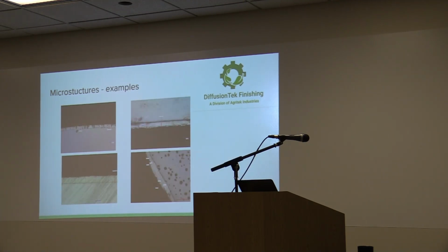Here's some other, we talked about the micro cracks a little bit, I think when we talked about sealers. And you can see in some cases these dark areas are some of the micro cracks. Now, this one probably shows it better. There's not very many. Part of our coating development was, I don't really like those. I want to get rid of those. What can we do to the formula to mitigate those kinds of things? That happens to be ductile iron. So those are graphite nodules, those round nodules.